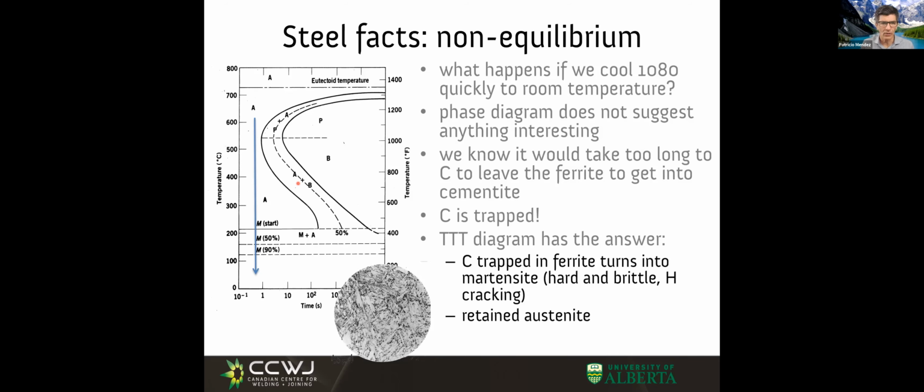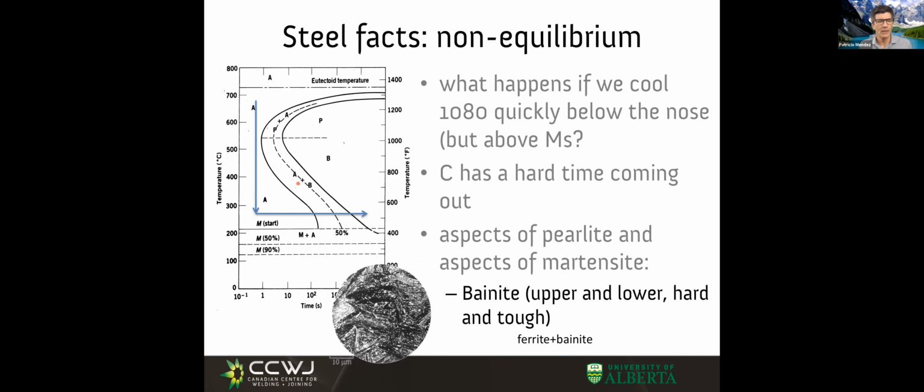And then what we saw is that if we don't cross the martensite line, but we do a transformation at low temperatures that is not martensitic, we get this hybrid that is kind of martensitic and kind of pearlitic, that has some amount of diffusion and some amount of transformation without diffusion, and which we call bainitic transformation.